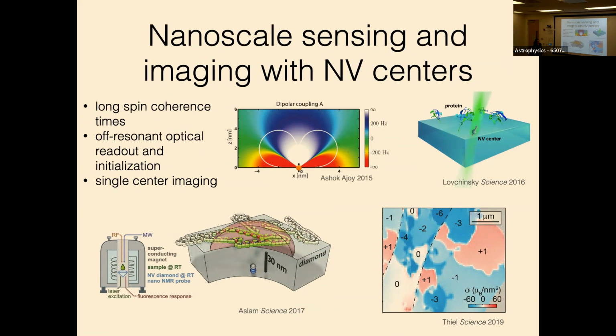Because the defect itself is really a true point defect, you can imagine doing things like looking at dipolar coupling between this electron spin and other things that are in the lattice. For example, if I plot here dipolar coupling strength as a function of distance, you can see that these contours change very, very rapidly over extremely short length scales. One way to think of this is it's a lot like magnetic resonance imaging, except you have the largest possible magnetic field gradient because you're really starting with a point sensor.